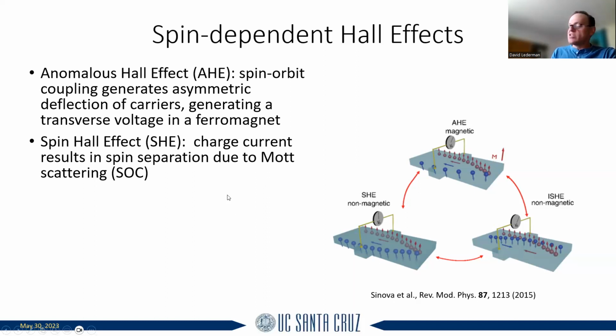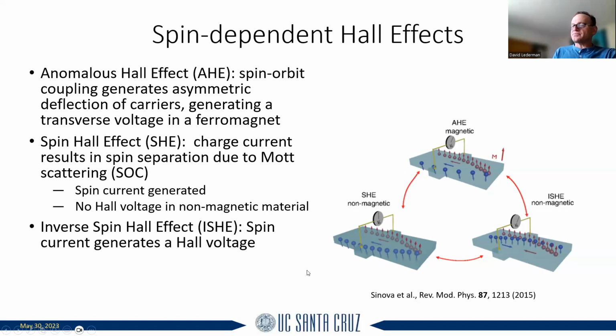Okay, and then you can actually have the inverse spin Hall effect, which is if you run a spin current like this, which could consist of spin ups going this way and spin downs going this way. It's kind of like the inverse of this. In that case, you end up with a voltage in this direction when you run a polarized current going in this direction and this direction with opposite spins. There is no net charge current, right? So it's a net spin current, but you would get a voltage like that.